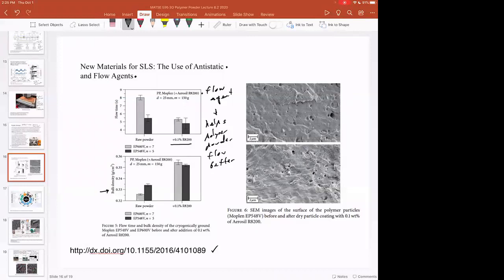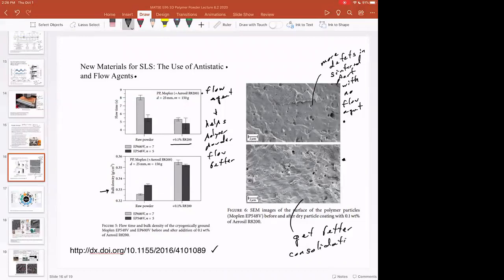And so when they looked at the before and after, you can see that there's more defects in the sintered part with no flow agent. Now, that's not to say that there's no defects once you put the flow agent in there. You get rid of some defects, you get a more consolidated part, so you can get better consolidation with flow agent. That doesn't mean to say that there's no defects in the part on the bottom, but it's a lot less.